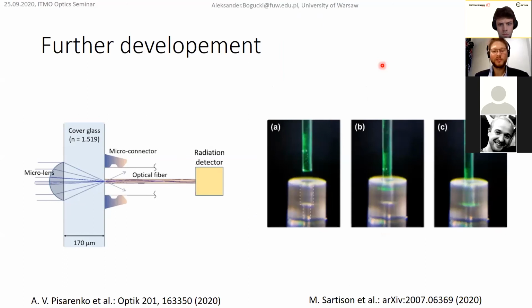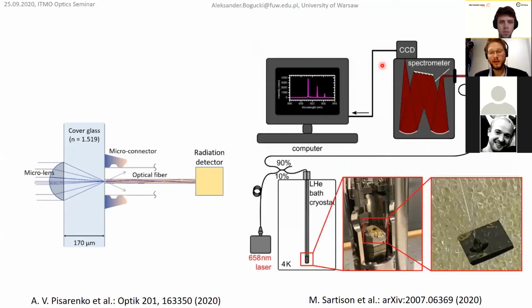So these are images from an optical microscope. And again, inserting the optical fiber is pretty easy. And they were measuring them as well in a liquid helium bath cryostat, similar to ours, with UV cured resin. This is the stack and the probe. It was in a helium bath cryostat, and they were measuring single quantum dots on that.